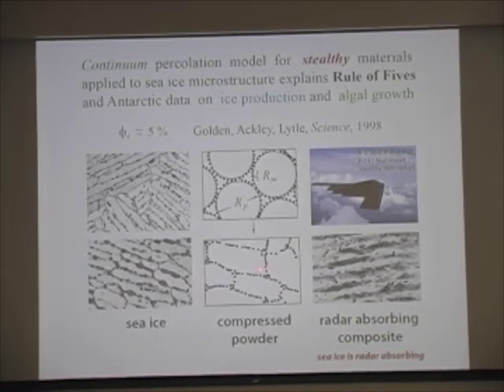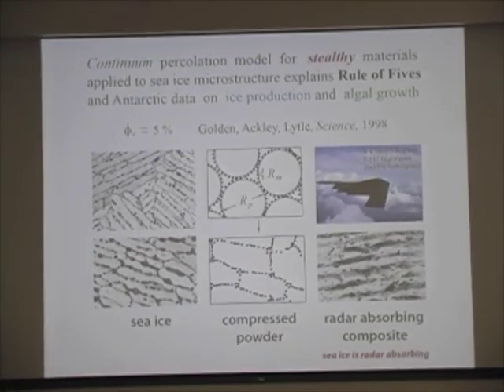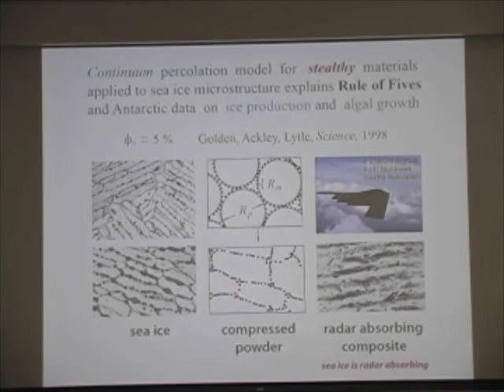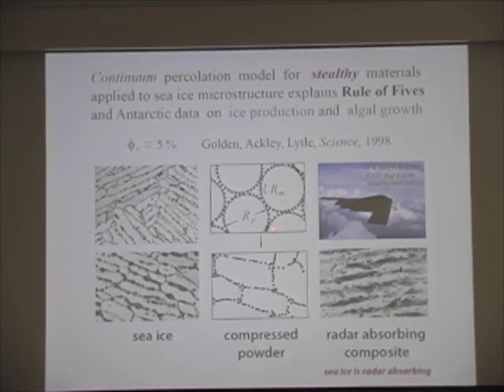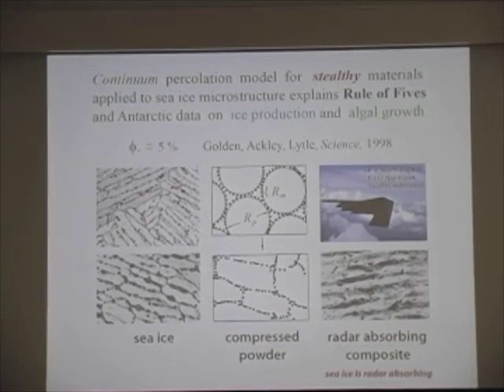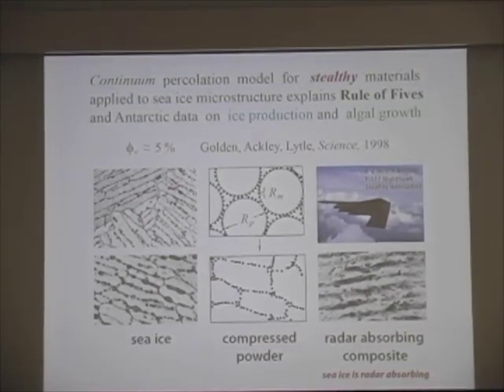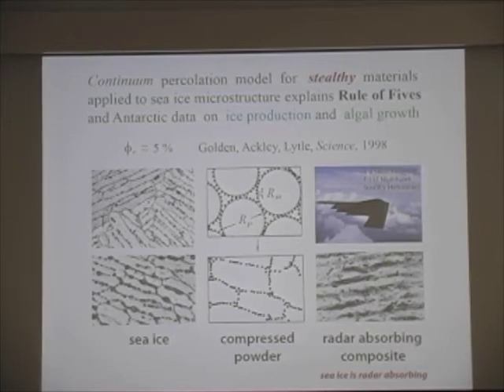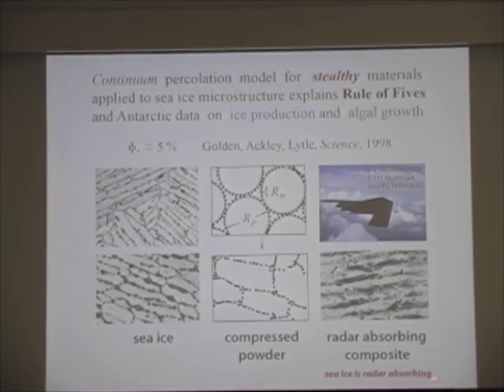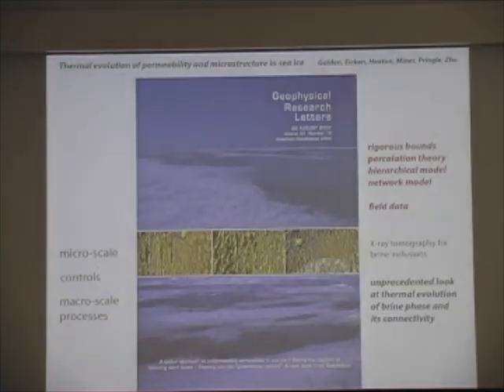And so basically all I did was I realized that these two microstructures were exceedingly similar. I took a mathematical continuum percolation model developed for these compressed powders, applied it to sea ice, and out popped this 5% value. So we were able to theoretically predict it, which then explained all kinds of biological and climatological data. And as a result of this connection, sea ice is a radar absorbing composite itself. It's very difficult. That's one of the reasons why measuring the thickness of the ice is so difficult. Radar waves, or radar waves of the frequencies that satellites use, just get absorbed. So this is one of the holy grails of climate science, to figure out ways of getting large scale information about the thickness of the ice.